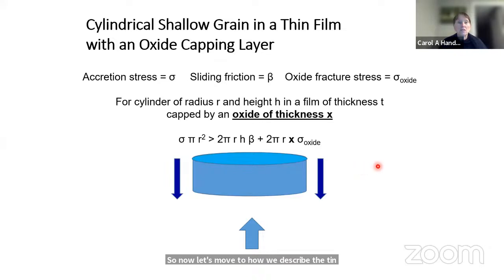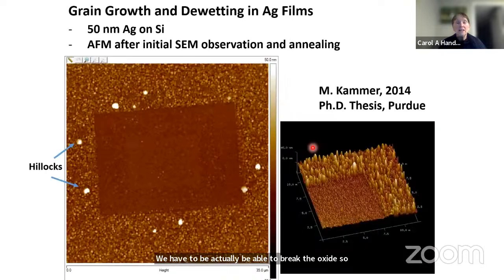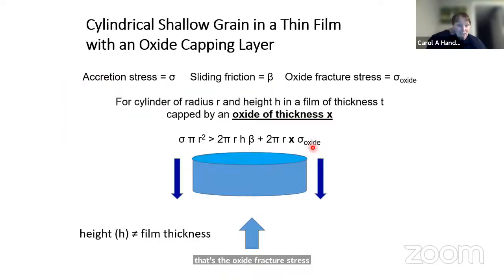And so we have again this cylindrical grain, and we also have an oxide layer on the top surface. So not only does the accretion stress have to be greater than the grain boundary sliding stresses, we also have the oxide. We have to actually be able to break the oxide. So that's the oxide fracture stress. And so we come up with a set of equations that describes what that trade-off should be.